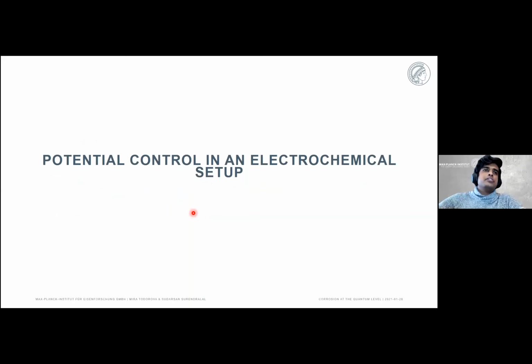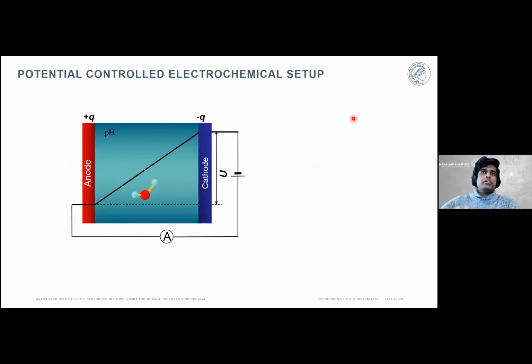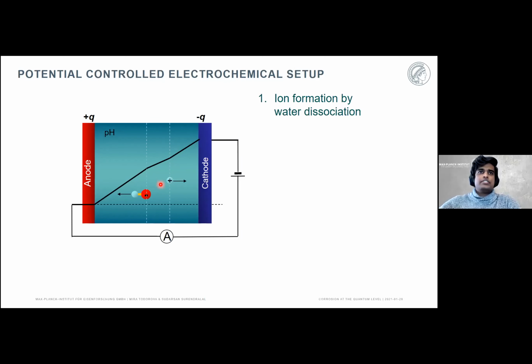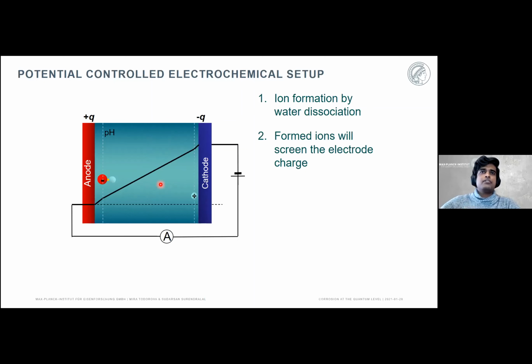Now, in order to motivate this portion of the talk a little bit, we need to know what potential control in an electrochemical setup actually means. So in order to understand that, consider an electrolytic cell with an anode and a cathode, which is maintained at a potential difference U. Let's say you have an aqueous electrolyte between the two electrodes. If there is a dissociation event, let's say where a water molecule splits into an H plus and an OH minus ion, what would happen initially, because of the potential difference, is that the ions would migrate to the electrodes, the anion to the anode, and the cation to the cathode. What happens as a result of this migration is that there will be a certain amount of screening by these ions. So if the initial potential that was maintained by the potentiostat was U, because of the screening, this would be reduced by an amount of delta U.